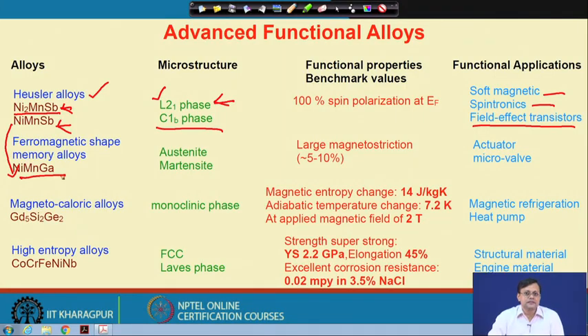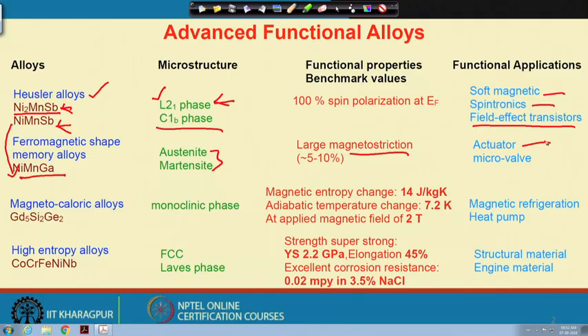However, in this particular case, we can get a shape memory behavior. They have, on one hand, ferromagnetic properties, and by application of a magnetic field, only ferromagnetic materials can heavily interact with the magnetic field. So, that is why they are ferromagnetic, and there will be a phase transition between austenite to martensite or vice versa, and we can get a very large shape change, dimensional change or length change. The property is called magnetostriction. So, very high, meaning greater than 5 to 10%, and these materials are already being used as actuators, micro valves and so on.